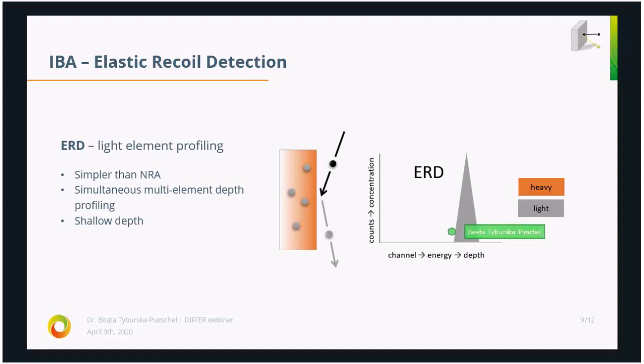And so you can then measure the hydrogen and deuterium concentration. It's actually simpler than NRA, and you can perform multiple element depth profiling. However, because the beam is coming under a grazing angle, the depth of penetration is very shallow, so you can only analyze maybe half a micrometer of your sample.